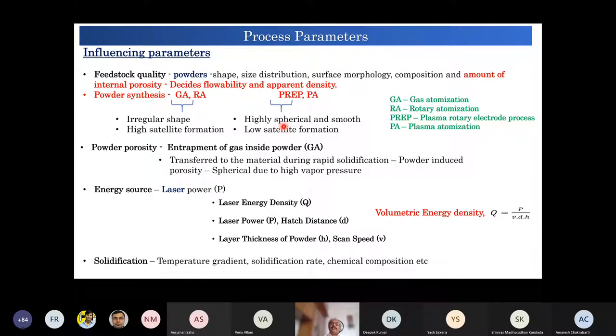So this is for the green pack, right? When we make the powder bed. But the main issue comes is the internal porosity. So when we are making powders, based on the processes that we use to make powder, in that case we can have internal porosity and slight deviation in geometry of the powder. For example, if we get powders from gas atomization or rotary atomization, which are the most common and economically feasible processes, there the powders are irregular in shape, and there is a satellite formation, which I will show you in the next slide, where small powders get deposited on the powder.